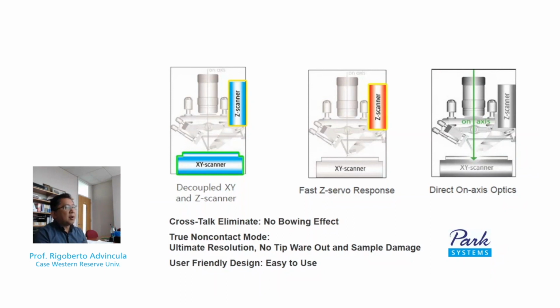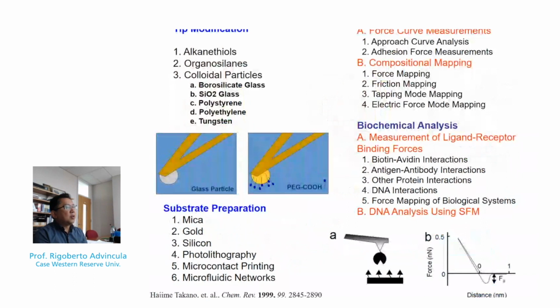And as a disclaimer, we actually have a Park AFM system and extend that we use. But otherwise, this summarizes the things you can do on an AFM. You can actually modify the tip so it can be sensitive to the surface by organic media or different types of functionalization, including particles at the cantilever tip.